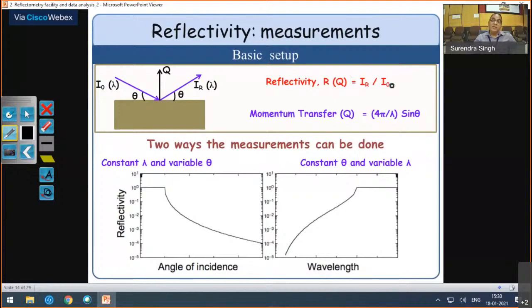This is exactly what we measure in our experiment, as a function of Q, which is perpendicular to the surface, along the depth of the sample. That's why we get the depth profile. Q is nothing but 4 pi sine theta by lambda, where theta is the angle of incidence and lambda is the wavelength of the wave.